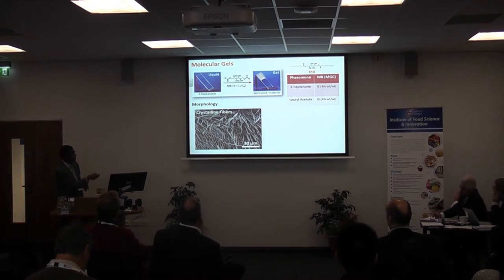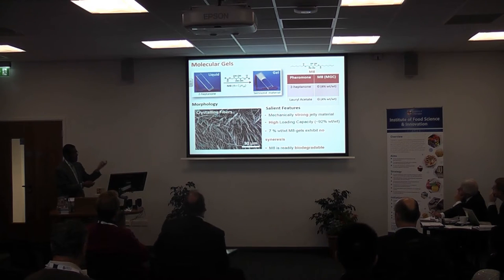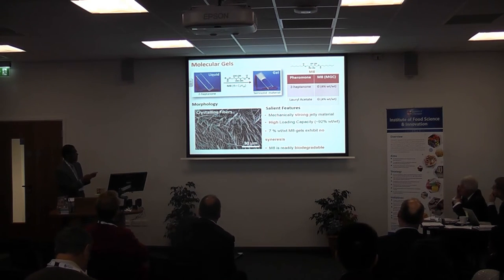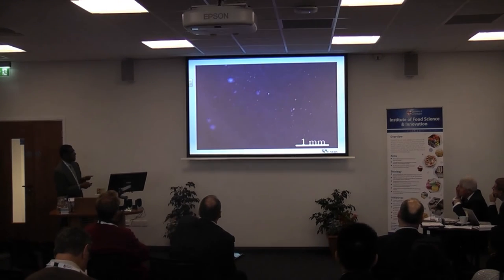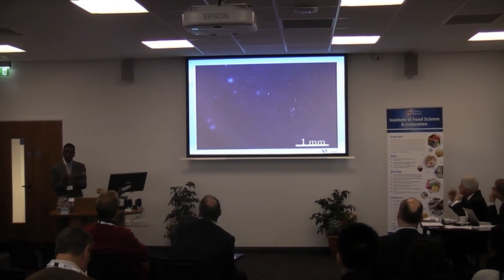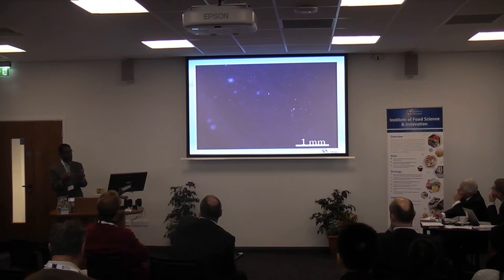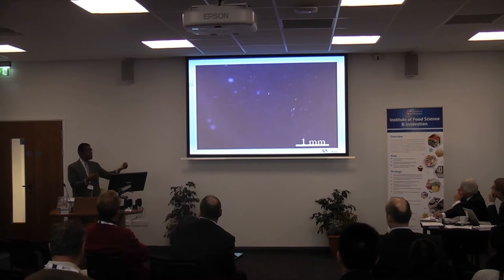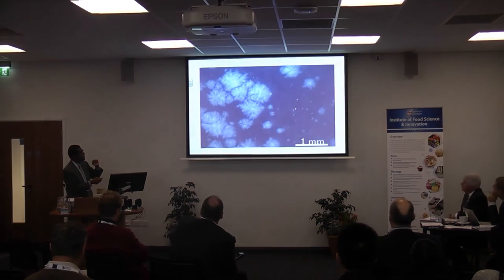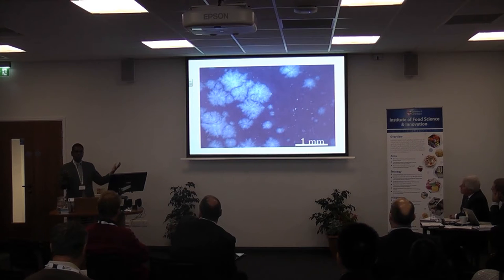And again, the gel is a three-dimensional network. It can encapsulate the pheromones efficiently, and we can release them very efficiently, with very little waste material. It is a very small molecule, non-toxic and safe. And when you are talking about jellies, how is it happening? These molecules start nucleating. You can see there are so many nucleation sites in the initial stage, but after some time they grow into a three-dimensional network. That is exactly a jelly.